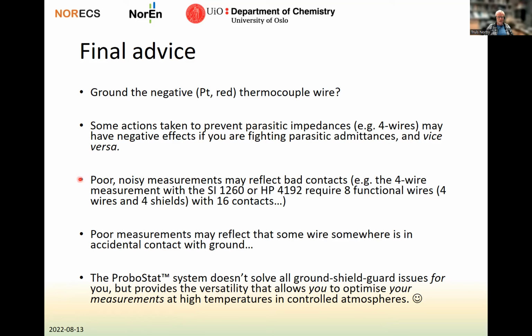If you get very poor and noisy measurements, it can typically reflect bad contacts. For instance, remember that the 4-wire measurement with a Solartron or Hewlett-Packard requires 8 functional wires, because you need the 4 wires and the 4 shields together, and both of them have contacts in both ends, so you need 16 functional contacts, and one of them can easily go bad or corroded or a loose wire. So check that there is conduction through all the wires and all the shields.